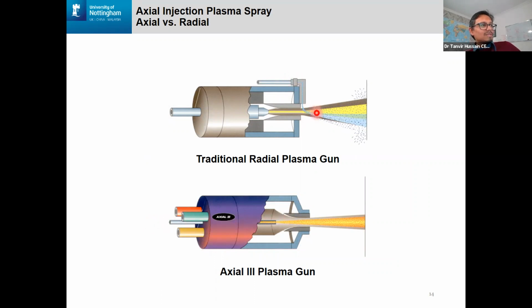There are some systems traditionally used to inject it radially, but the challenge with radial injection and suspension is these suspensions of the powders can overshoot or undershoot the plasma. And as a consequence, a lot of these particles could be outside the hot zone of the plasma. As a consequence, you have got a sustainability issue. A lot of the particles may not deposit and contribute to making these thermal barrier type coatings we're talking about here.